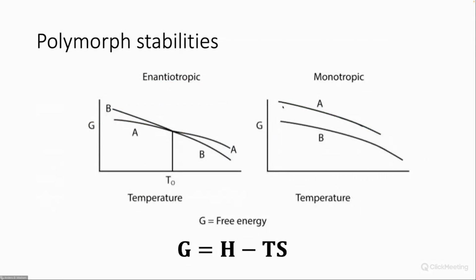And that's all related to what we call polymorph stability, and we can draw these enantiotropic and monotropic diagrams of the free energy as a function of temperature. So if we have two polymorphs where the free energy curves cross, we have a change in the thermodynamic stabilities, and we see here in this diagram, for example, that the A form is more stable than the B form at low temperature. And at higher temperatures, after this phase transition point here, we have B as the most stable form. Whereas in other cases, we will have a monotropic relationship between the polymorphs, and for example here we have B as the most stable form at all temperatures.